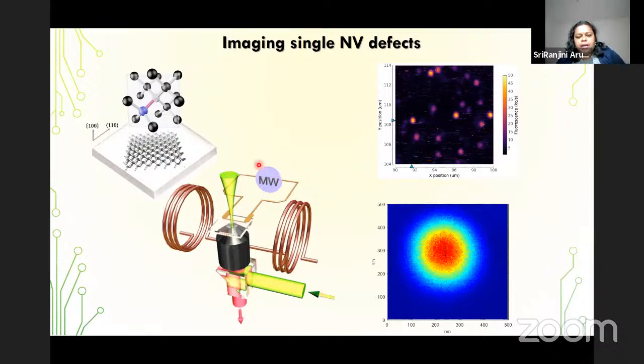This is the schematic diagram of how the experimental setup in our lab is. This is a closer view at the microscope objective. So this is the objective, and this is where we have the diamond with NV centers incorporated into it. We apply a green light which passes through this, and which emits a red light which can be collected through this geometry. On a horizontal plane, we apply a microwave to manipulate the fluorescence reading, and then a coil is also kept in order to apply an external magnetic field whenever necessary for the experiment.